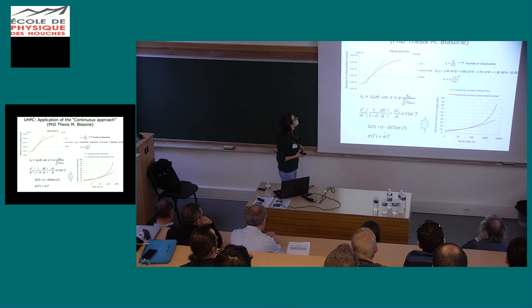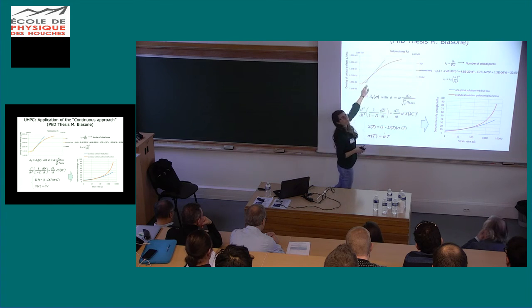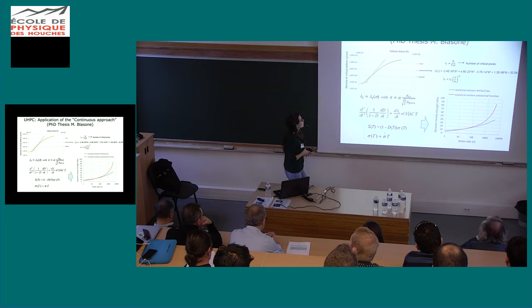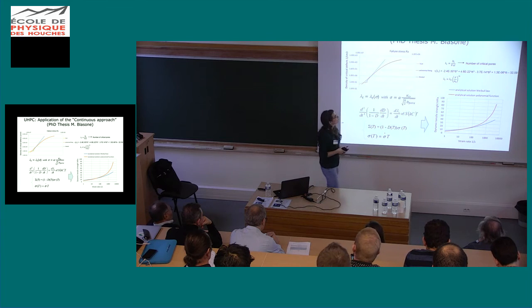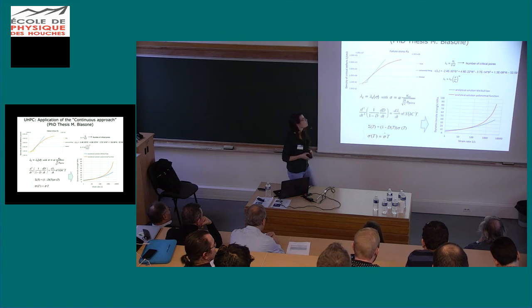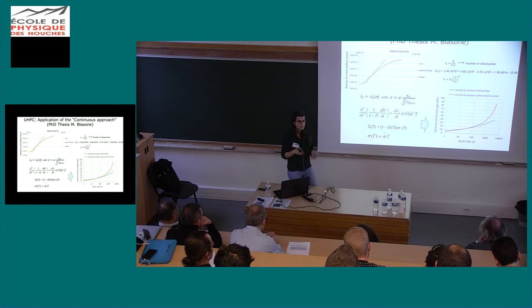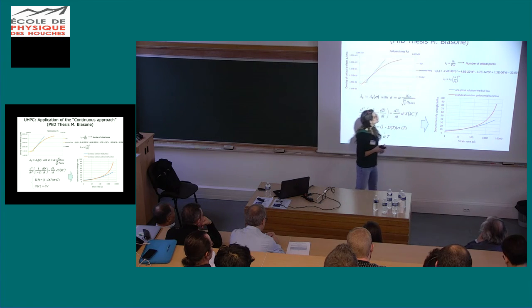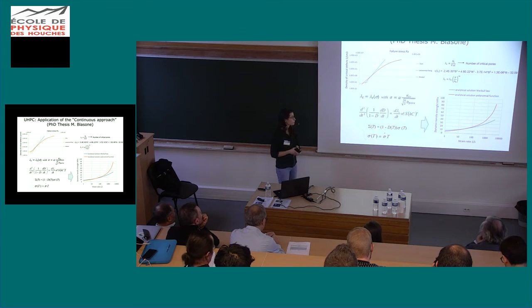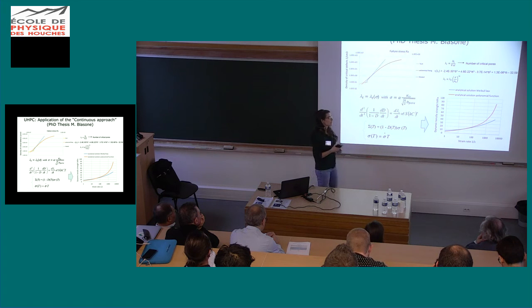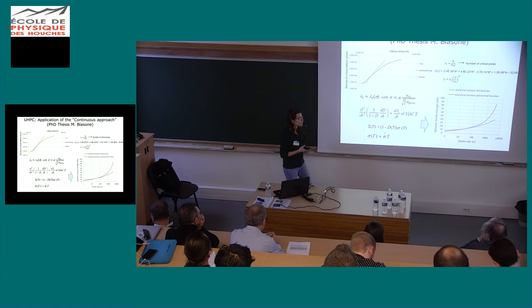Now we have in this graph the density of critical defect that we get using the quasi-static test, and the density of critical defect that we get directly from the scan. So what we can try to do is to extract a polynomial function that fits our population of critical defects that are extracted directly from the scan. And then we can try to use the model that Pascal has explained to extract a value of dynamic tensile strength for each strain rate.